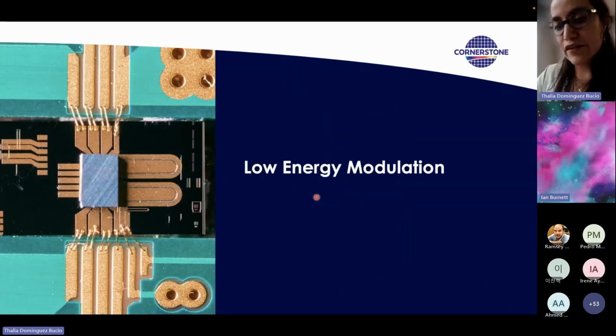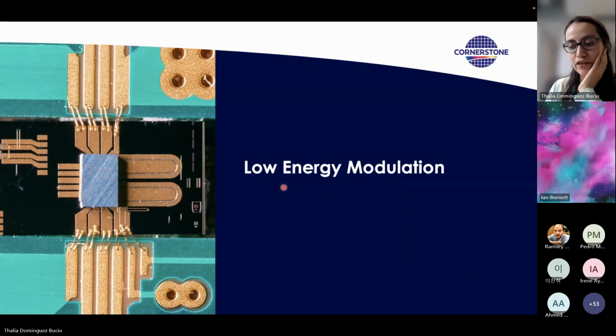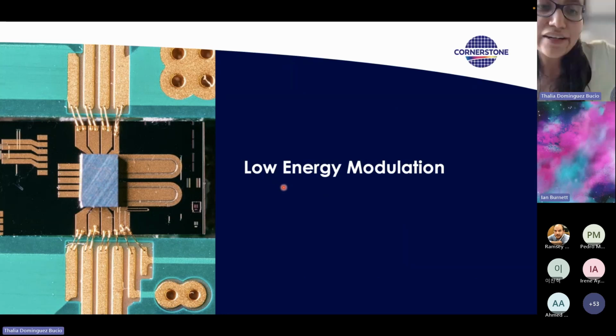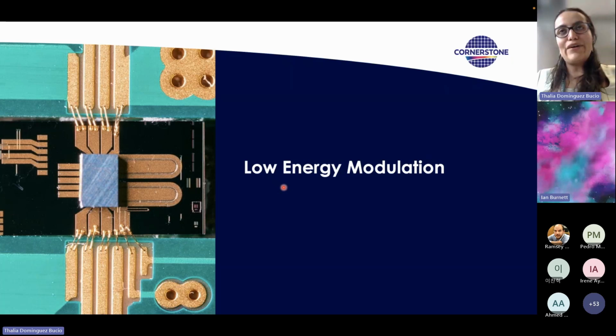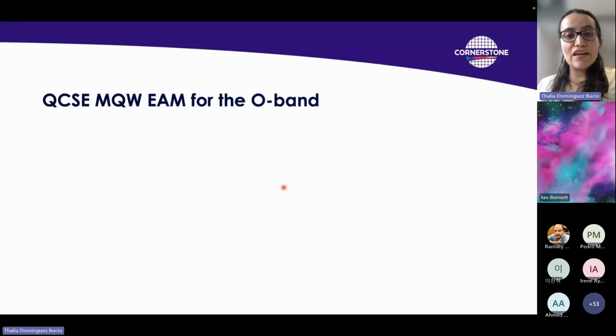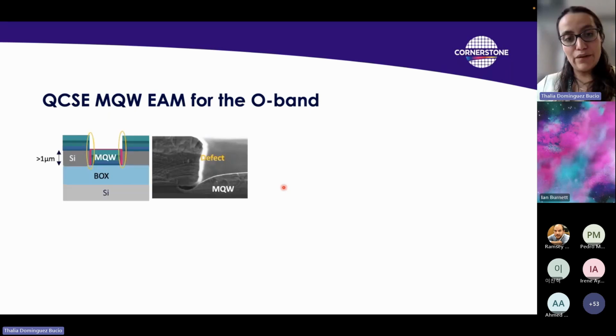To start with, I'm going to discuss a little bit about low energy modulation. When we talk about low energy modulation, we are talking about integrating modulators that can consume very low energy in our silicon nitride. And as I mentioned before, with silicon nitride itself you cannot do active devices. So what you have to do is integrate it with a material that can achieve this modulation. In this case, one of the applications is to achieve electroabsorption modulators in the O-band by integrating the silicon nitride layers with multi-quantum well stacks of silicon germanium.